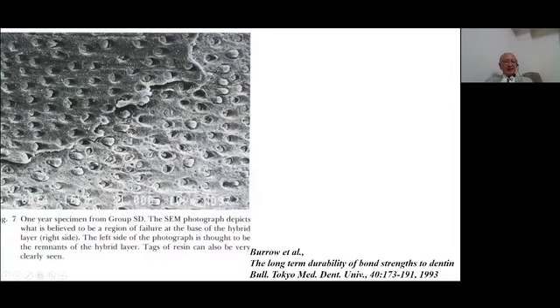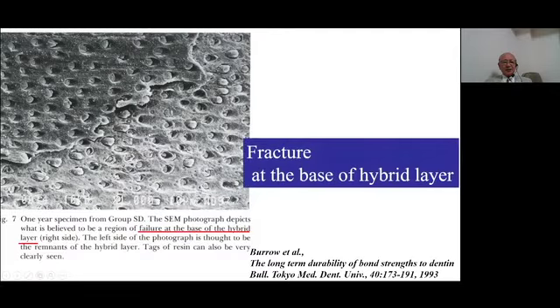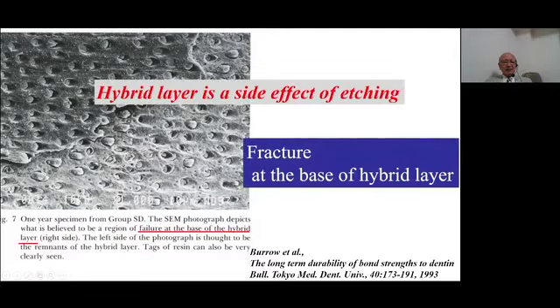When we evaluate the bond strength after the storage in water for 1 year, this strong etching material shows the debonding at the bottom of the hybrid layer. So we can say that the hybrid layer is a kind of a side effect of the etching. Of course, we should try to create the high quality hybrid layer.